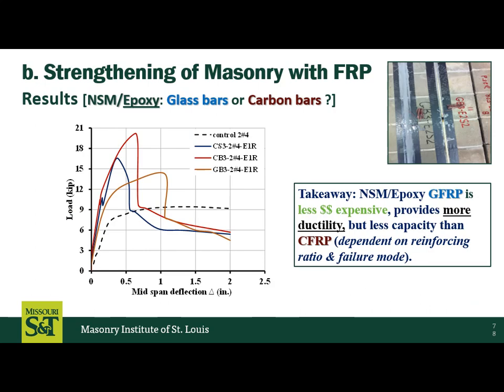I'm just going to give you some takeaways. There's references to reports you can look up and papers if you really want to dive into it. But first of all, near surface mounted with epoxy in these bed joints, what's kind of the takeaway? Well, if I compare CFRP, the C is for CFRP, the G is for GFRP, we see the CFRP gives us higher capacity than the GFRP. That's because it's 300 KSI, right, versus 100 KSI, so we would expect that.